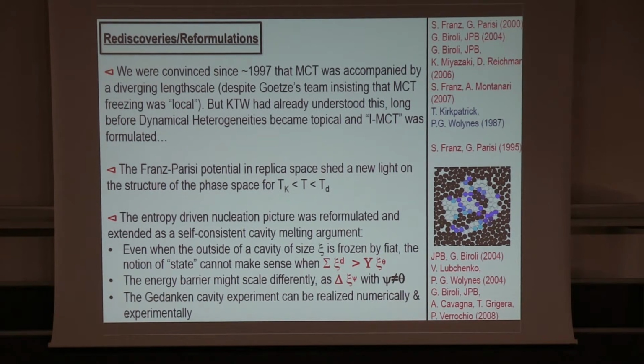So we were also convinced around 97 that mode coupling theory was accompanied by a diverging length scale. And actually, Goetze and his team were always insisting that mode coupling theory was purely local. It was the formation of local cages with no diverging length scale accompanying the dynamical slowdown, or dynamical arrest, actually, in the theory. But again, KTW had already understood this. In one of their papers, many years before dynamical heterogeneities became topical, they have somewhere in their paper a diverging susceptibility and a diverging length scale around the dynamical temperature.